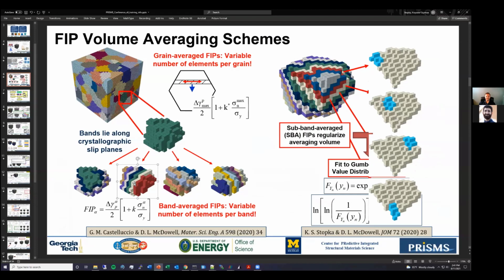So when we band it and then we calculate our subbands, the way the code works is for a given band, it will start with 1 element and then locate the distance to all the neighboring elements. And then it will designate a subband as the unique set of elements that has the 7 or 8 closest neighbor elements. So you can imagine if there are a lot of elements per grain, this code will take a long time to run.